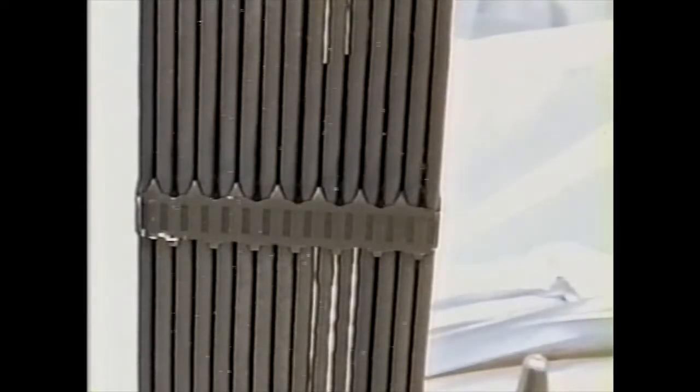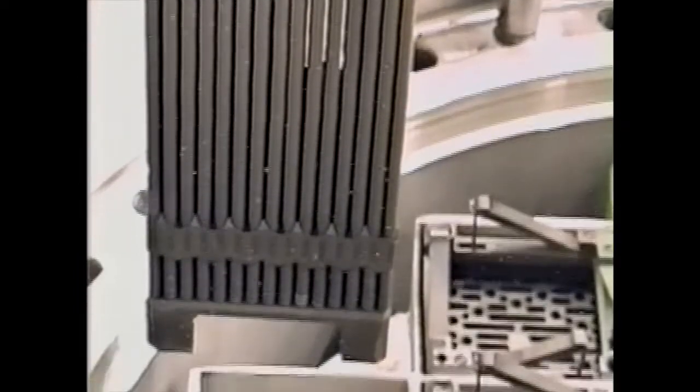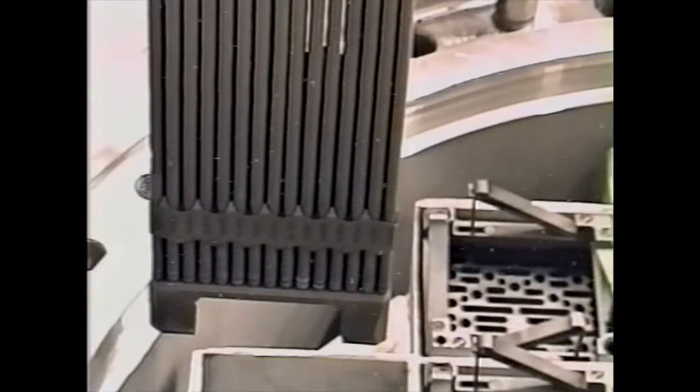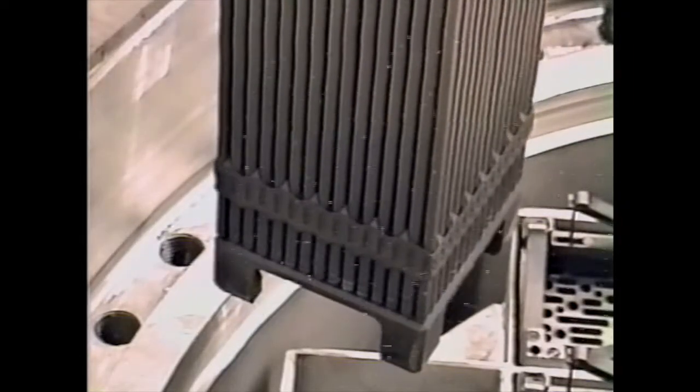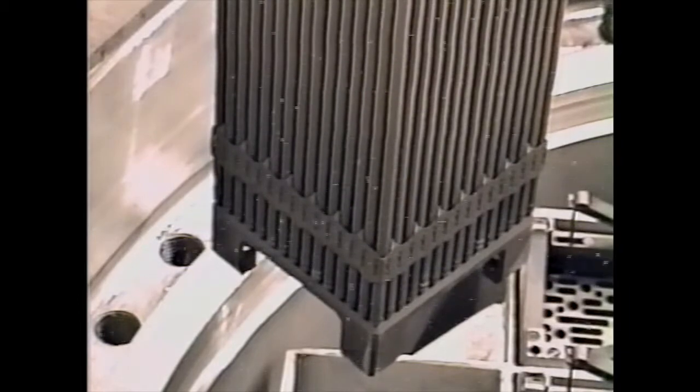The double layer structure of these surface oxides was inferred from the mottled appearance of the surface of the rods at the grid spacers. The inspections found no increase in the oxide layer thicknesses, no formation of a loose oxide scale, and no accumulation of loose oxide scale or particles between the fuel rods, on the grid spacers, or on the bottom nozzle.